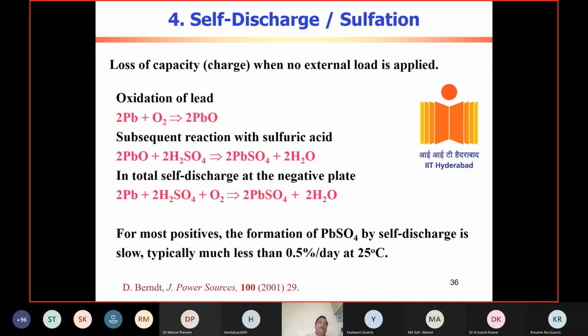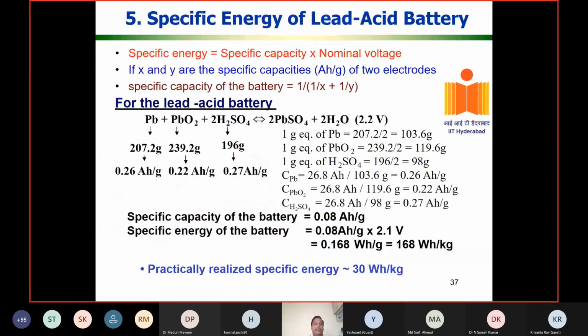Another important thing is that if you leave the battery in a charged condition or discharged condition, you still have self-discharge. Because, as I told you, you are using a water-based electrolyte, aqueous sulfuric acid, which is 4.5 molar. Oxygen evolution and hydrogen evolution always take place. So oxygen combines with lead to form PbO, and PbO reacts with sulfuric acid to form PbSO4. This is the discharge product. So PbSO4 is formed. That means you will see around 10 to 15% per month in a lead-acid cell, even more in some cases. So this is one area where you can work. I'll come to that.